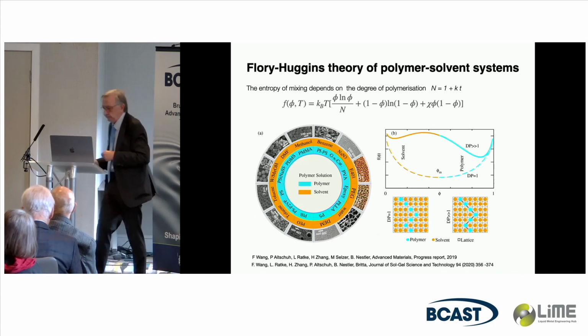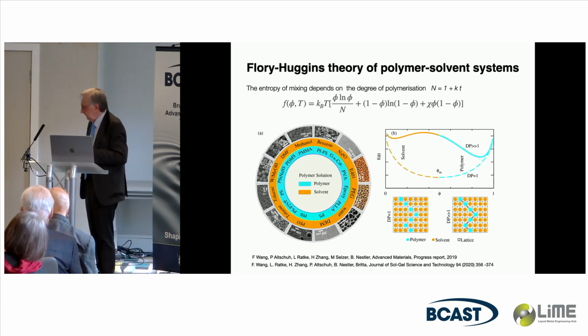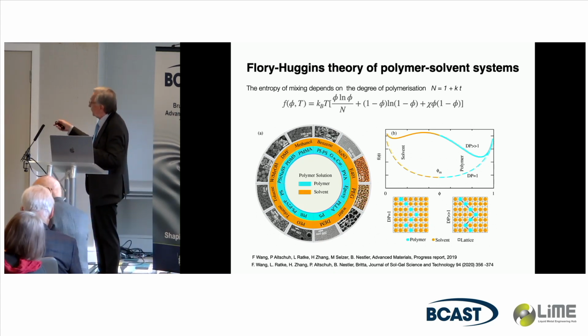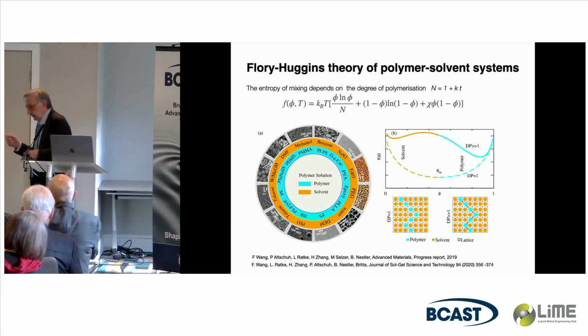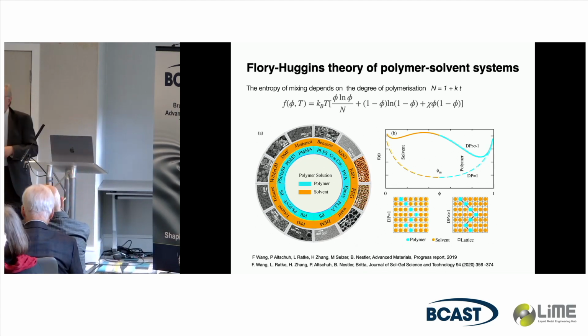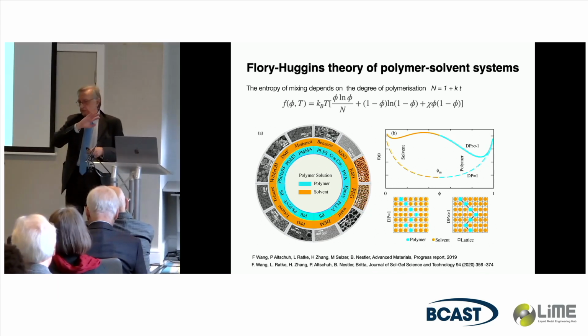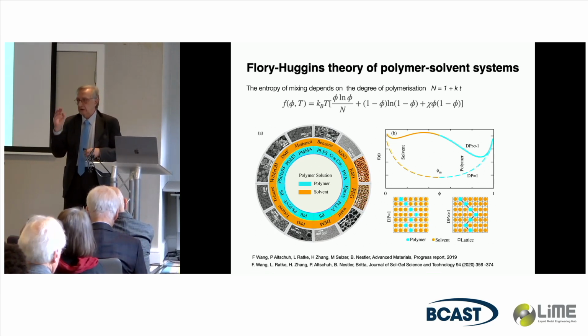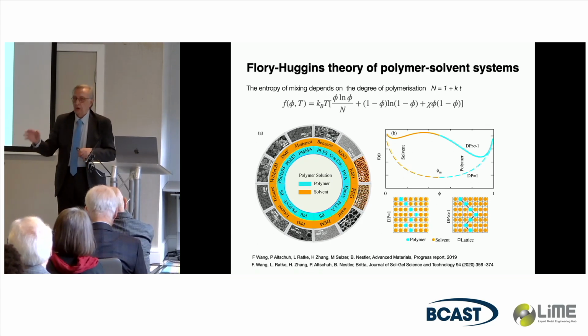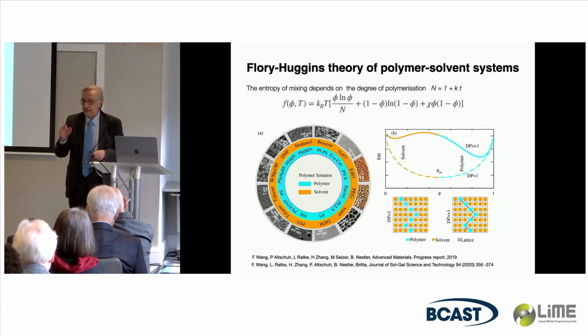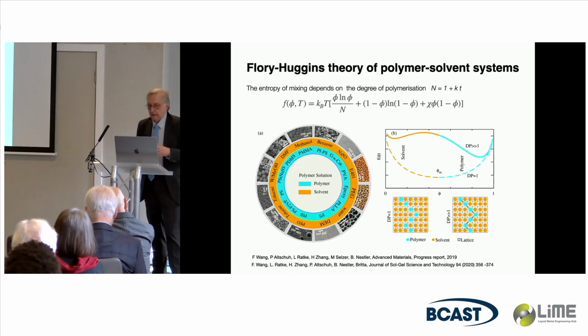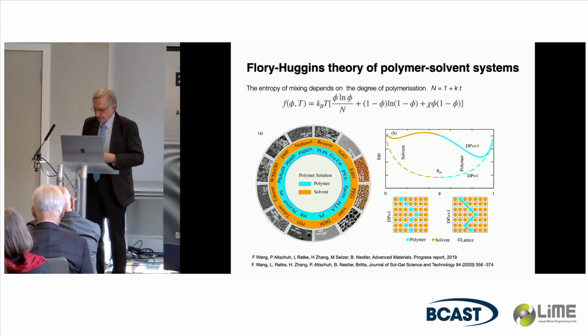even in the nanoscale, depending on the polymer and of course on the solvent used there. And see this, the degree of polymerization is linear in time. This is not an estimate, this is exact. If you calculate polycondensation, you really find out that the degree of polymerization always increases linearly with time, and not with a cube root, a square root, or whatever power. It is exactly linear in time. If you do not believe, I can show you how to calculate that.